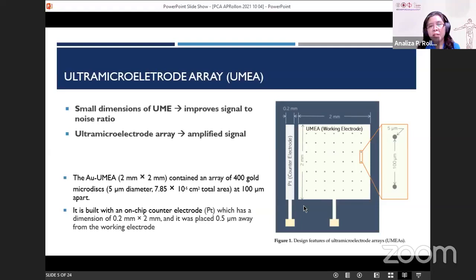So here, this is actually the ultra microelectrode array that we use in the study. So this array is composed of gold ultra microelectrode array, 2 millimeters by 2 millimeters, containing 400 gold microdiscs, and each disc here has a 5 micrometer diameter, and these are 100 micrometers apart, center to center distance, and it is built with a counter electrode, which is this dimension given here, and it is placed 0.5 micrometers away from the working electrode.